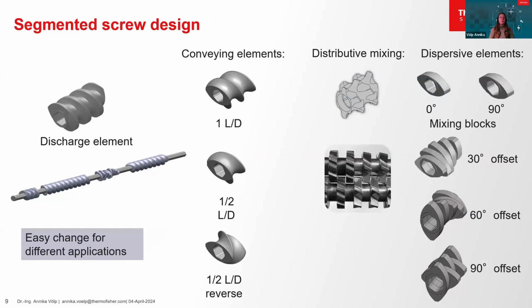Here you see screw elements like the discharge element that increases the pressure at the die entry here on the left, conveying elements with various lengths and conveying directions, distributive mixing elements that mix with minimum shear, and dispersive mixing elements that apply increasing shear force with increasing offset angle when arranged in mixing blocks. Those elements are arranged like beads on a string to fulfill a specific series of processing units. An example for this is shown on the next slide.